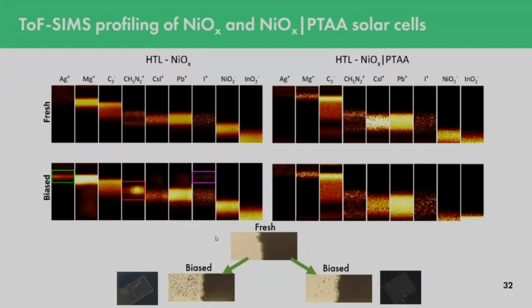For example, in the red frame, you can see that all organic parts, like the formamidinium cation, are not in their rightful place. After the degradation, almost all of it is concentrated in the fluorine derivative part. And also you can see in the green frame that silver plus is quite brightened after the degradation, and at exactly the same level you can observe the iodine anions, in the purple frame. We can assume that after the biasing we have migration of iodine ions towards the silver electrode and corrosion of the silver electrodes, because it's very reactive towards iodine.